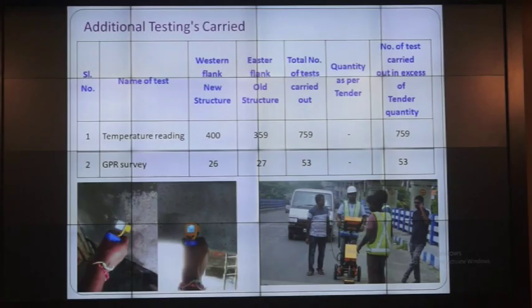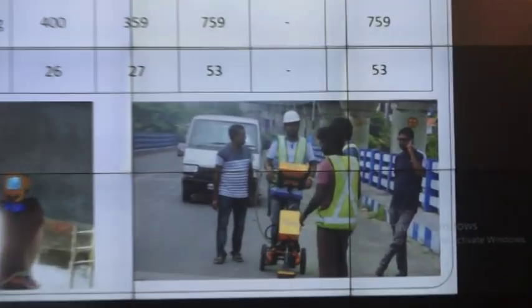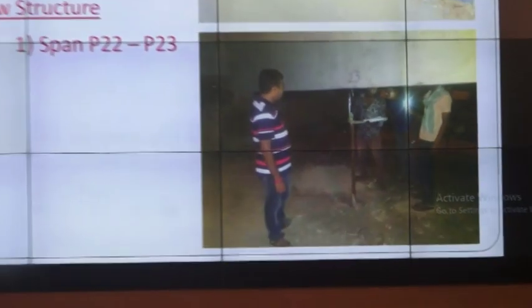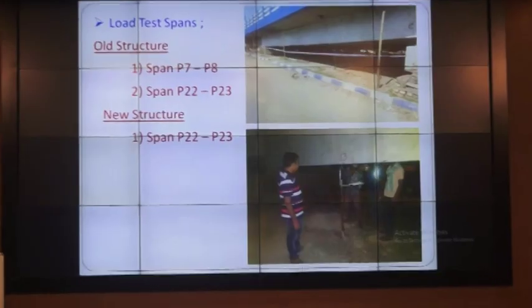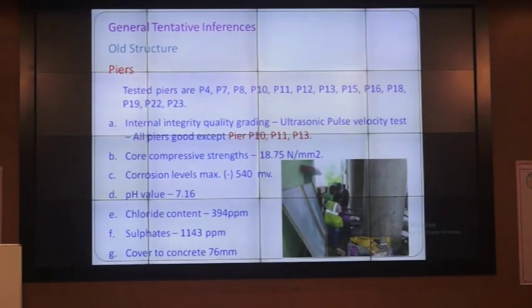On the right side you see the GPR in action, ground penetrating radar. That will give you any delaminations in the slab. If there is some delamination, whether your 200 mm or 220 mm slab thickness has horizontal or vertical delaminations somewhere, the equipment in your right side photograph will show you all that. And the left one is the temperature measurement. These are the load test spans we have selected, for the load test.